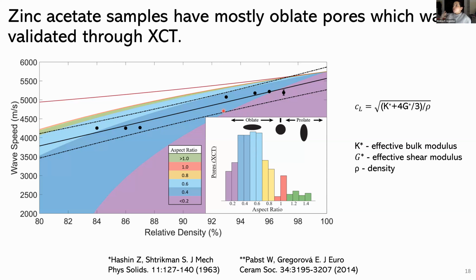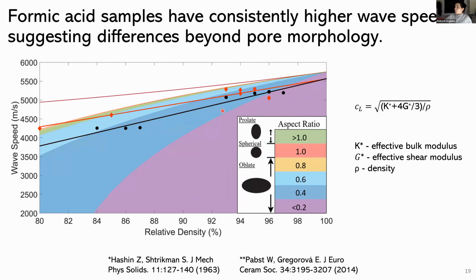So this already gave us some initial information on the type of quantitative data that we were able to gather just based on the ultrasonic analysis, and the combination of that with these micromechanics-based models that tell you more about the morphology of the microstructure that we're dealing with. But another thing that was interesting and that we're still in the process of exploring is that once we started looking at the formic acid samples, you see that they no longer quite fall into that oblate pore category.